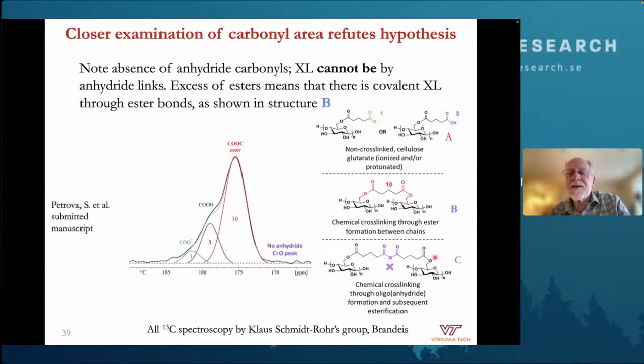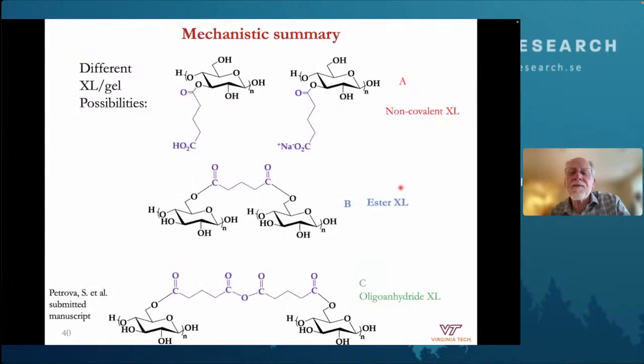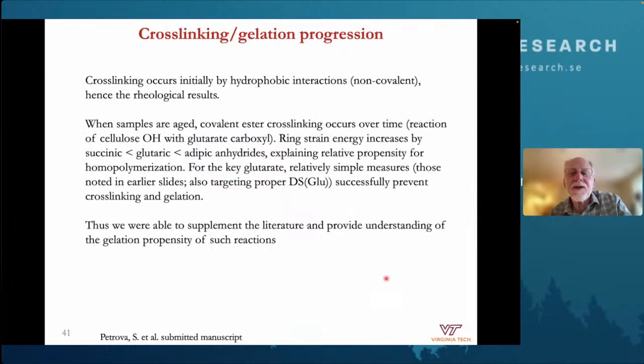The excess of ester bonds means that probably what's happening is ultimately we're getting ester cross-links. We're getting hydroxyl on one chain reacting with a carboxyl on another chain to make ester cross-links. So what we saw, we think, is initial formation of non-covalent cross-links. Those are the initial gels that we've seen. Over time, those develop into ester cross-links, and that anhydride cross-linking is not happening with these cellulose glutarates.